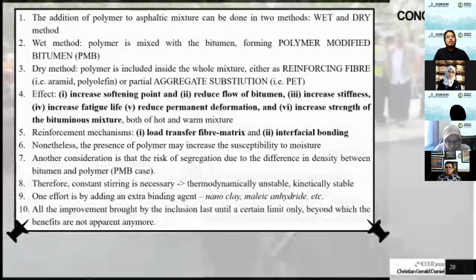These are the conclusions. With the wet method, we have polymer modified bitumen. With the dry method, we could have the reinforcing fiber or partial aggregate substitution. Then the effects are to increase softening point, reduce flow of the bitumen, increase stiffness, fatigue life, and strength, and reduce rutting, or basically the increase of stiffness in both hot and warm mixtures.